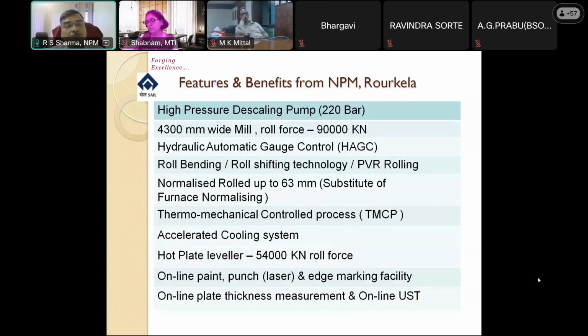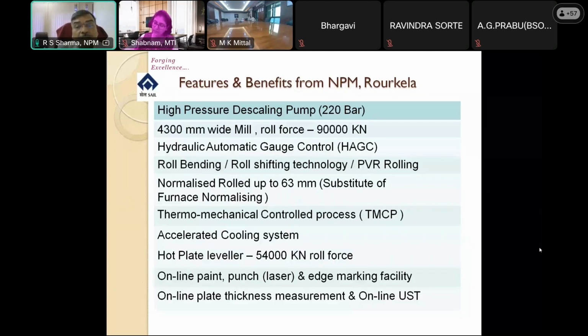This is the major USP of this mill. Whatever slabs we get, we roll with this force, and the reduction takes place right up to the center line. So there is a complete reduction, and voids and porosity are removed by this, ensuring the internal soundness of the plates. Earlier we used to give plates without UST, and those were passing in UST also. That was the contribution of the mill basically. Then in the mill we also have HAGC, hydraulic automatic gauge control, for controlling the thickness. This is a vital function and ensures the thickness across the plate width and length.